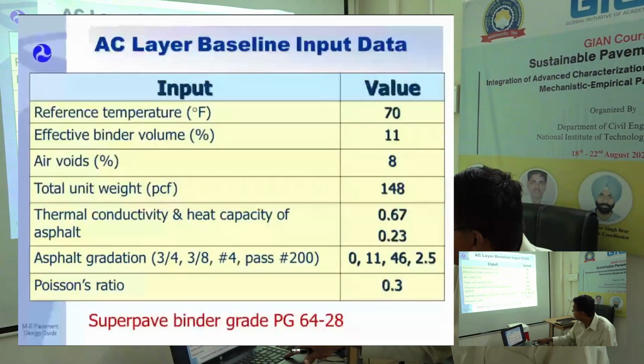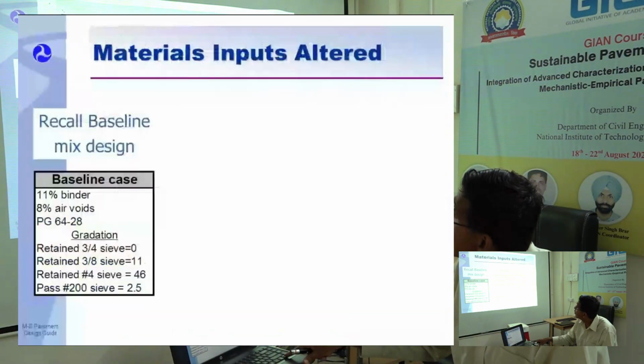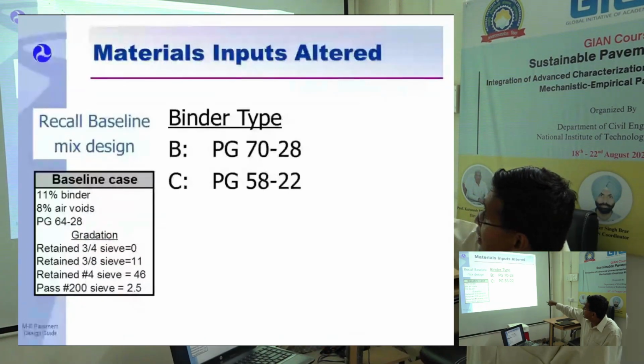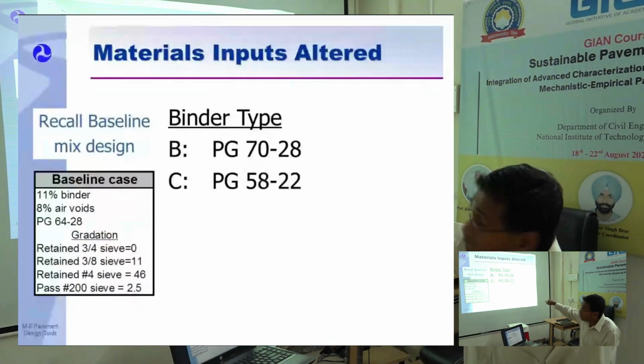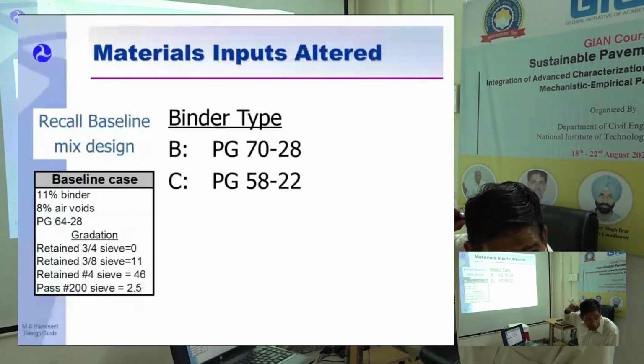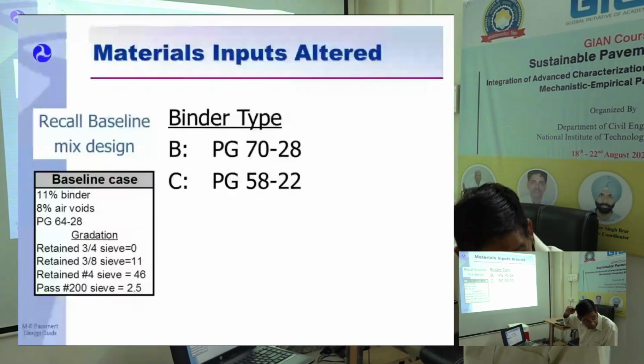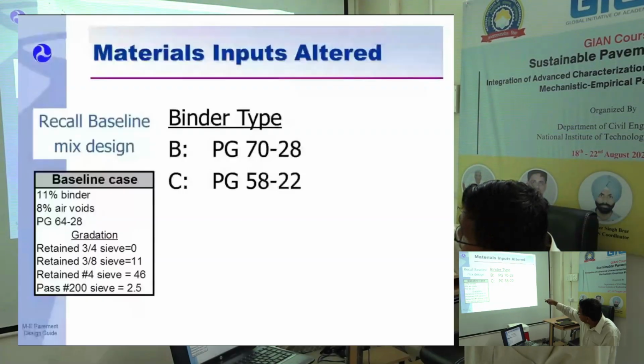Superpave binder grade 64 minus 28. Baseline mix design is here. Two binder contents, 70 minus 28, 58 minus 22. Does anybody know what 70 minus 28 means? Anybody? You got it. 70 is the high temperature, and 28 is the negative low temperature. It will crack. So the binder is good enough that as long as the temperature stays within 70 Celsius, it will not rut. If it stays above minus 28, it will not crack. 58 minus 22.